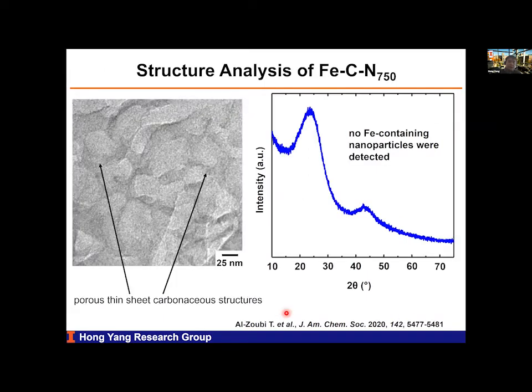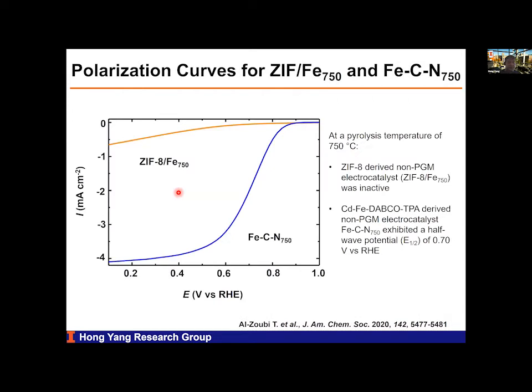So this is the result we obtained, and the XRD demonstrates no iron peak formations. And if you look at the converted carbon-metal matrix, you don't see nanoparticles. You will see evenly distributed contrast, typically suggesting the metal dispersion is quite good in the system. We did a comparison with the typical ZIF-8 derived ORR catalyst. If you look at the polarization curves in the iron-based system, for our system you start to see the activation already. But for ZIF-8 at 750 degrees, you do not see the ORR activity at all. So this is quite encouraging.